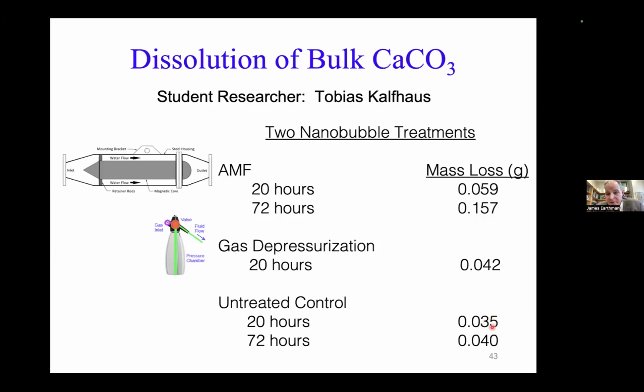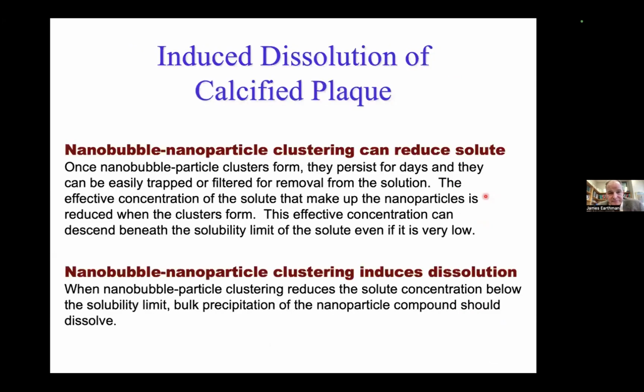Now we expected some loss because we start out with DI water. There's no calcium carbonate to begin with, so you're going to dissolve some calcium carbonate just to bring the concentration up to the solubility limit in the control. So that we expected, but it wasn't nearly as high as the mass loss we saw with the nanobubbles, especially with AMF. So this is our strategy. We form these clusters. We can force the effective concentration of the solute down below the solubility limit and start dissolving it as much as we want, as long as we can keep adding more and more nanobubbles.